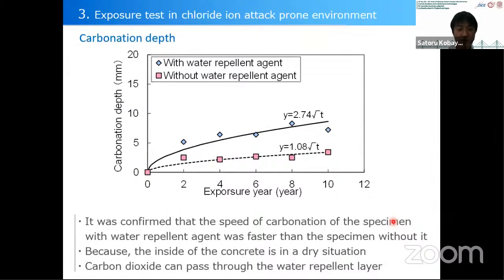This is a measurement result of carbonation depth. The horizontal is exposure year, and vertical is carbonation depth. It was confirmed that the speed of carbonation of the specimen coated with the water repellent agent was faster. The blue one, with the water repellent agent, was faster than the specimen not coated. Because the water repellent agent prevents the penetration of water, the inside of the concrete is in a dry situation, and carbon dioxide can pass through the water repellent layer. So it is considered that the concrete becomes easy to carbonate like this.